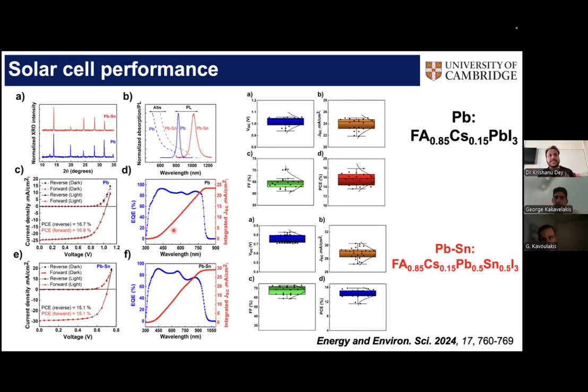So yeah, the thing is, the tin fluoride is added to basically suppress the formation of tin vacancies. And so tin vacancies give rise to hole doping. So if you don't use any tin fluoride, the material will be extremely p-doped. If you use some tin fluoride, they will reduce the doping. Now, beyond a certain threshold, this reduction is not much more significant. Let's say you go from 10% to 20%, the reduction is not significant. Secondly, it's been reported in the literature that if you use too much tin fluoride, the tin fluoride itself tends to segregate, and then they form some other kinds of defects, which are not good. Which is why generally in the field these days, 10% is kind of the maximum that people use for solar cells.